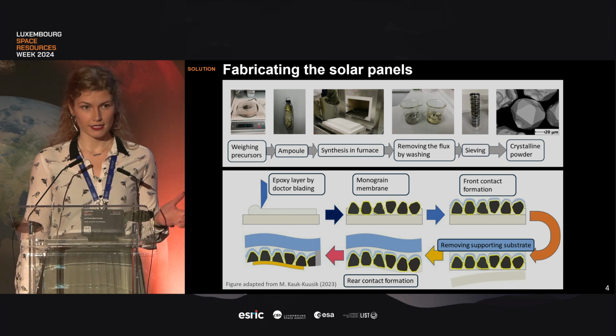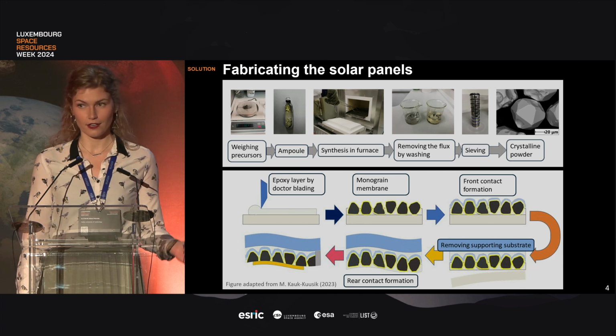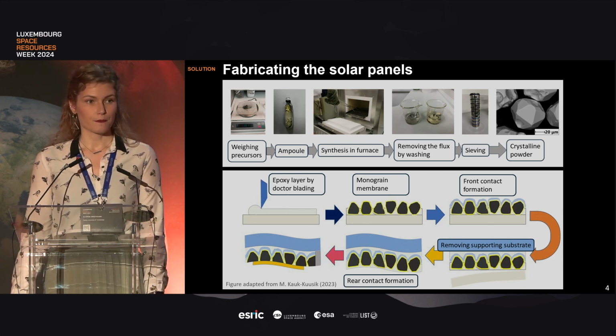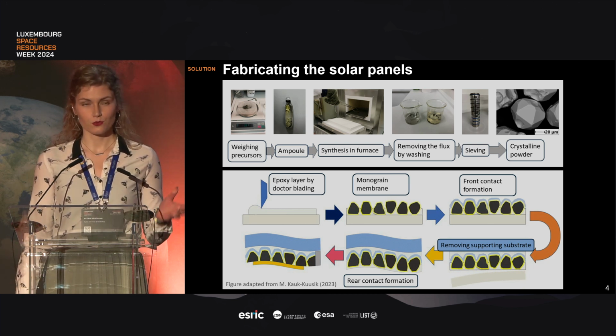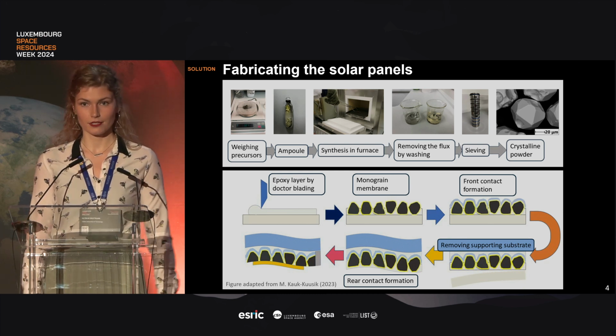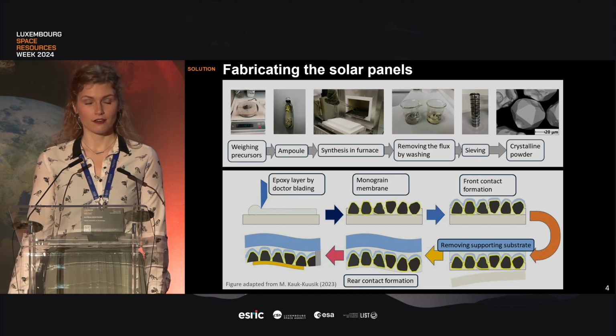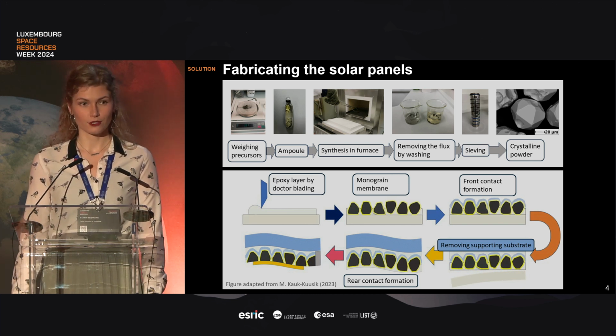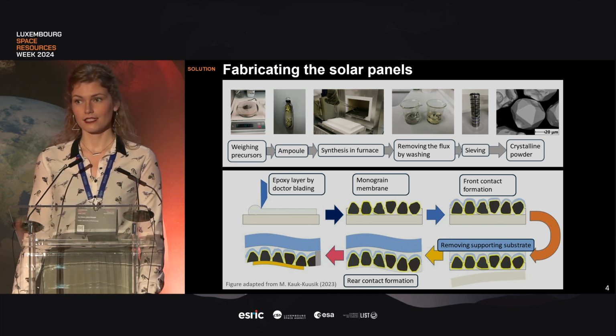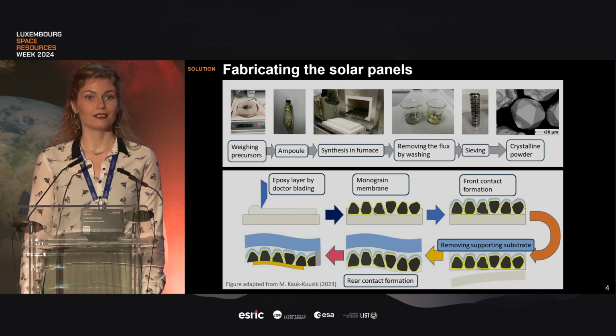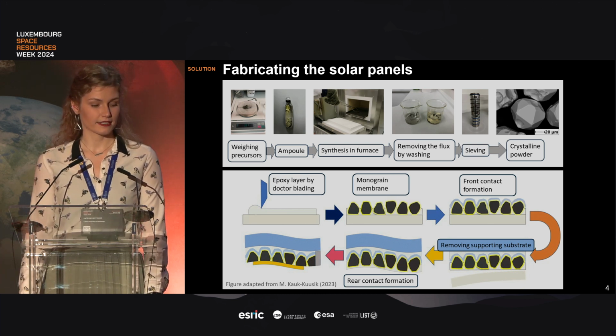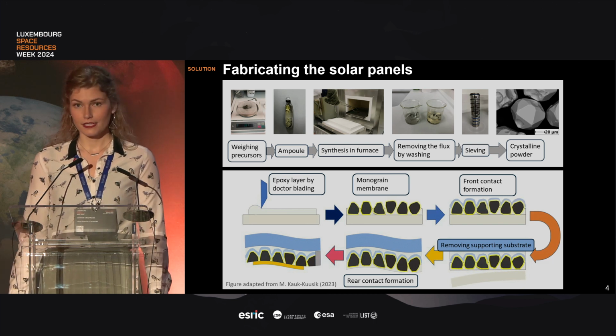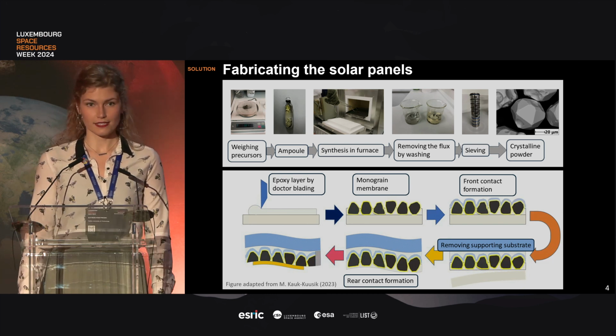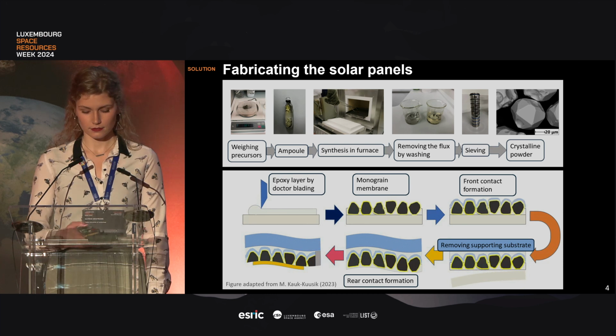Now, for the membranes, the crystals are embedded in a layer of epoxy or another polymer. The crystals are covered with a buffer layer or a p-n junction partner, if you're familiar with photovoltaics, and then covered with a transparent front contact layer. The backs of the crystals are revealed by polishing, and the back contact is added. That's how we make these cells. And none of these steps includes any very expensive or complicated equipment.